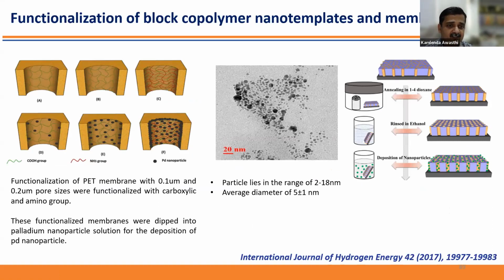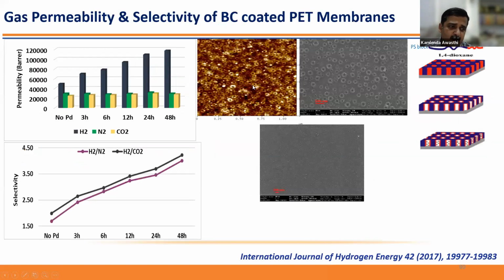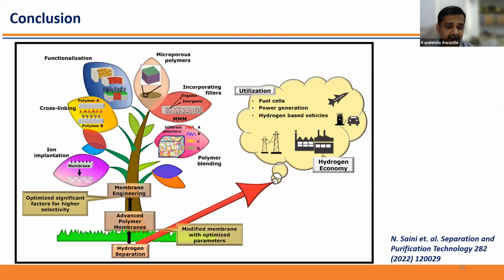Similarly, we tried the concept in this block copolymer nanotemplates. So we used the same strategy, carboxylic, then amine, then we bound this palladium nanoparticle. So when we have both layers, the supporting layer also with palladium and the upper layer also with palladium, you can see the selectivity of gases increases drastically from this to this, up to 48 hours. And this, you can see the template, and the white part, if you can visualize on the screen, these are the palladium nanoparticles. They are around this block copolymer nanotemplates. So in conclusion, we use our membrane in hydrogen separation. So this may be an advanced polymeric membrane, or this may be a modified membrane with optimized parameters.